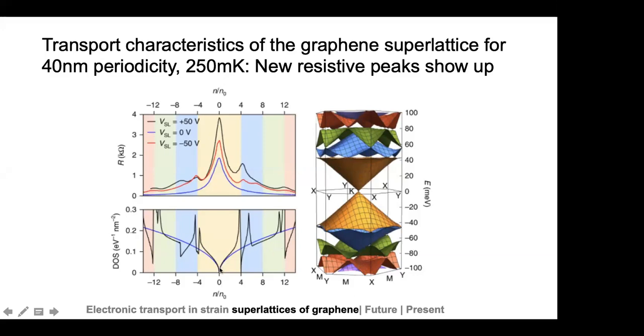And they also find that for the density of states, as compared to zero superlattice voltage, which is this blue curve, the density of states for a plus 50 volts superlattice curve varies quite a lot. So another thing to note is that these colored regions correspond to the different bands filling up in the band structure. So for example, this blue region corresponds to this blue band over here filling up with electrons. So that was interesting, which was seen. Some effects of a superlattice, which was created using a patterned backgate.